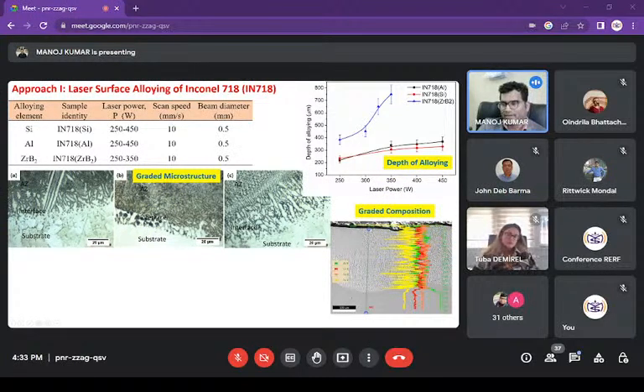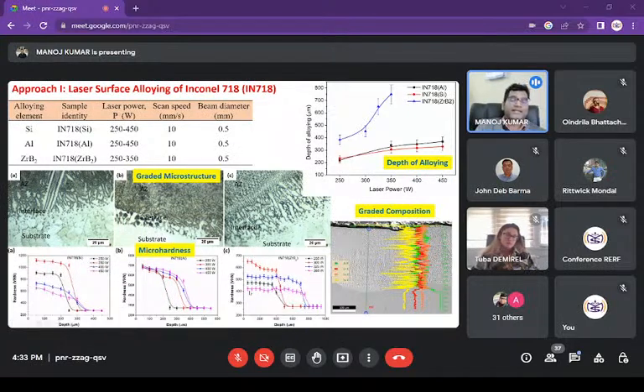We can see over here, this is for aluminum. In the alloy zone we find aluminum, but when we go to the substrate there is no aluminum. So we have got the graded composition and also the graded microstructure, and that results in graded properties. We have very high hardness in the alloy zone, slightly decreasing across the interface and reaching the hardness of the substrate, which is much lower than the alloy zone.